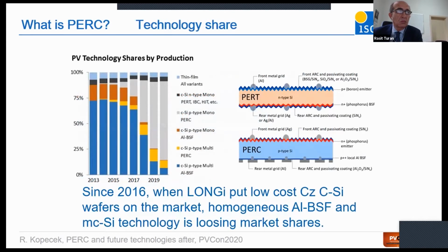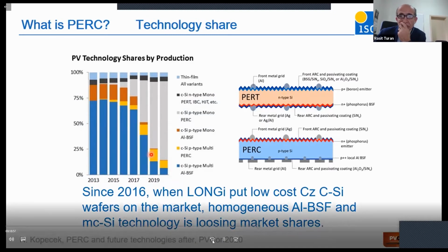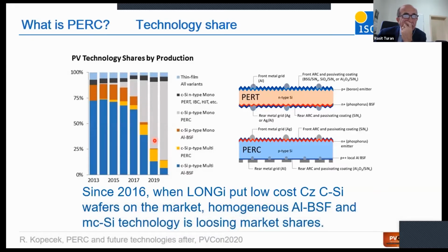On this slide, you can then see how the transition was performed from aluminum back surface field to PERC. So the aluminum back surface field are the blue bars, and PERC the rest. So since 2016, when LONGi put the low-cost wafers on the market, there was more or less a very fast switch to PERC. And now the question is when NPERT or TOPCon or heterojunctions will be so powerful that actually we will observe such a change to N-type. I think that PERC will remain still for a couple of years very powerful, but it can happen that N-types then take over.